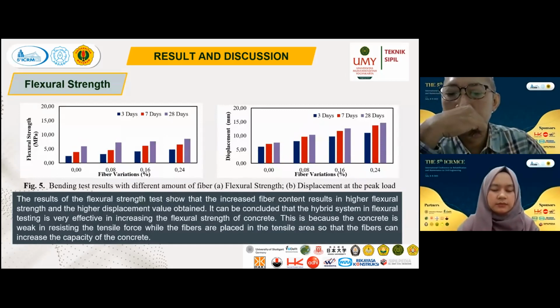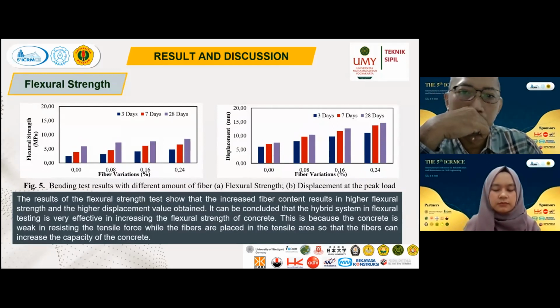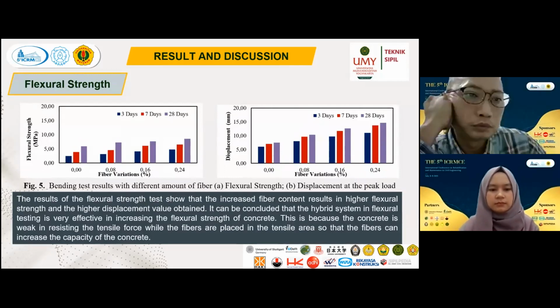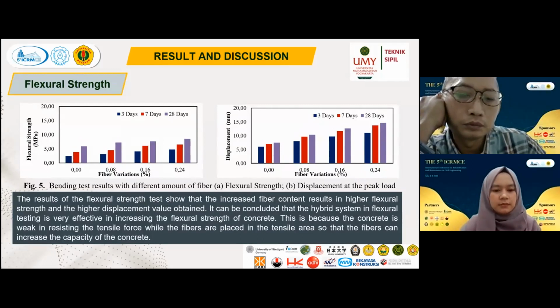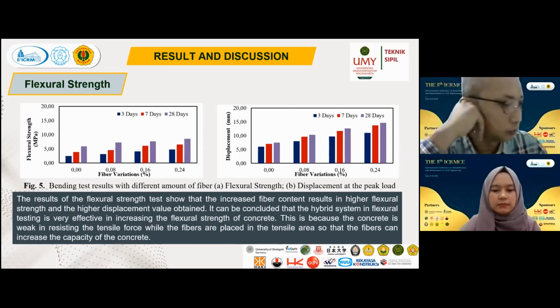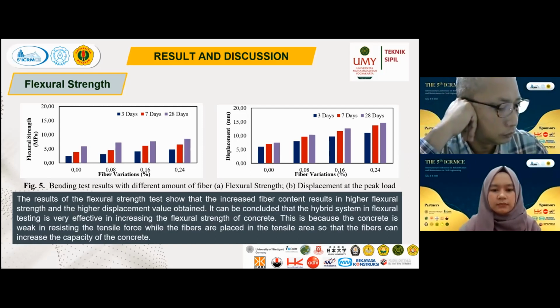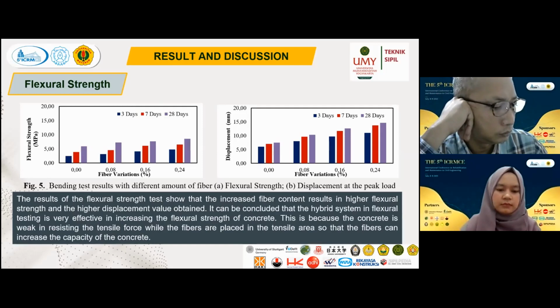And this is the flexural strength. The result of the flexural strength test showed that the increased fiber content results in higher flexural strength and higher displacement value obtained. It can be concluded that the hybrid system in flexural testing is very effective in increasing the flexural strength of concrete. This is because the concrete is weak in resisting the tensile force, while the fibers are placed in the tensile area, so that the fibers can increase the capacity of the concrete.